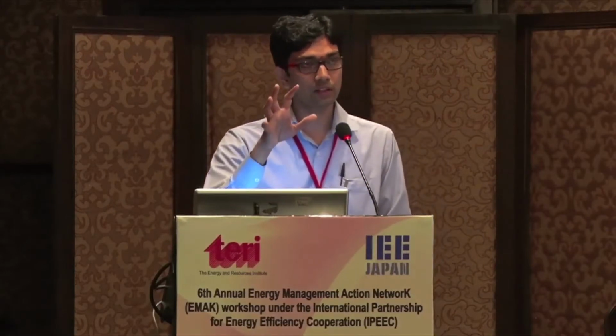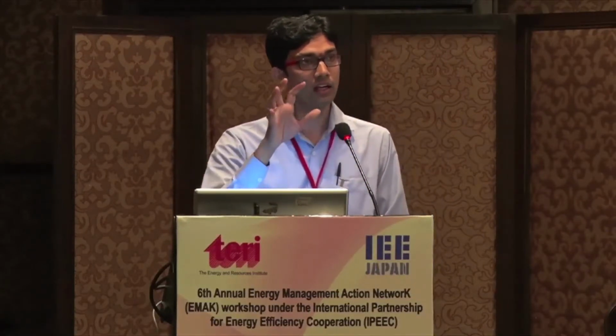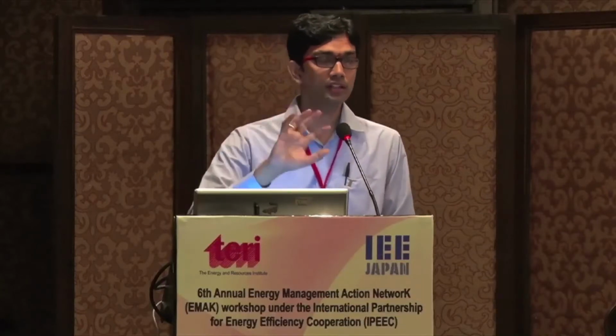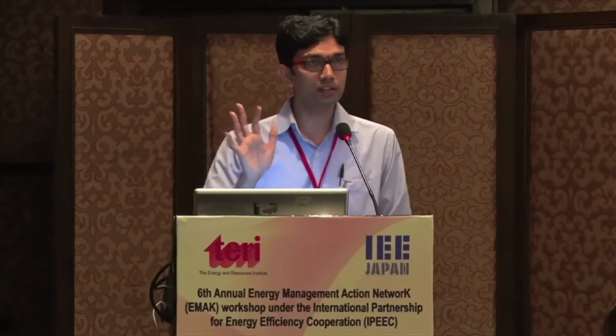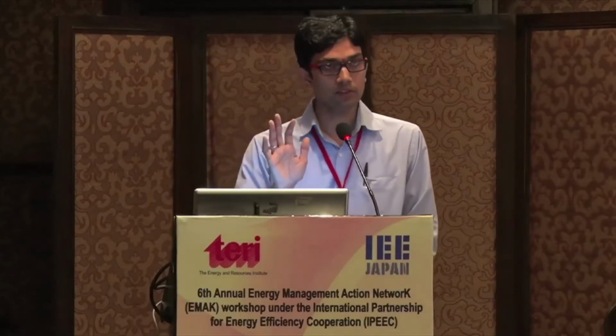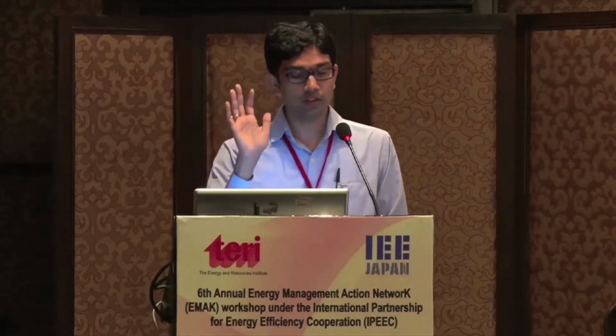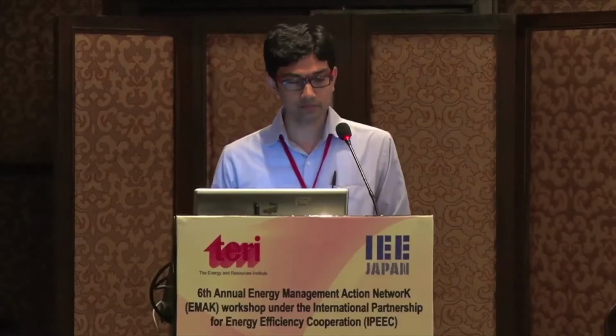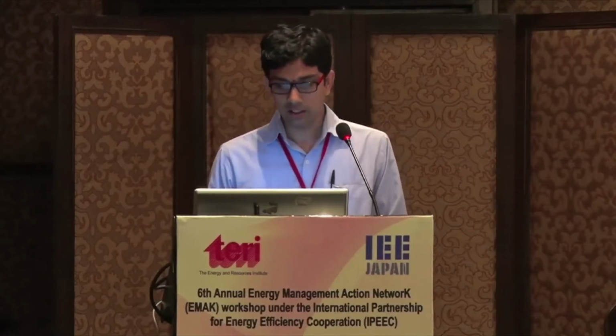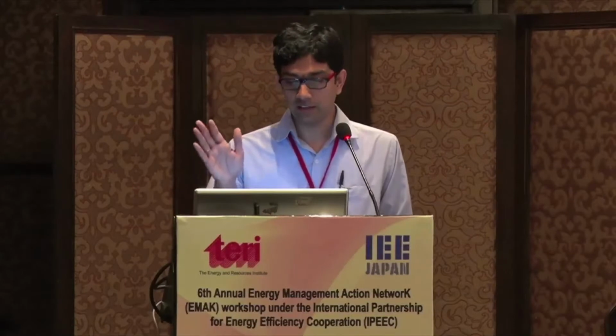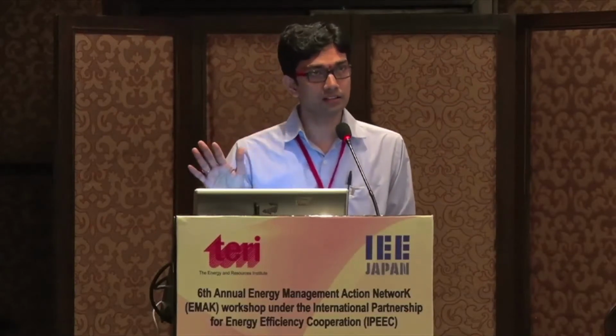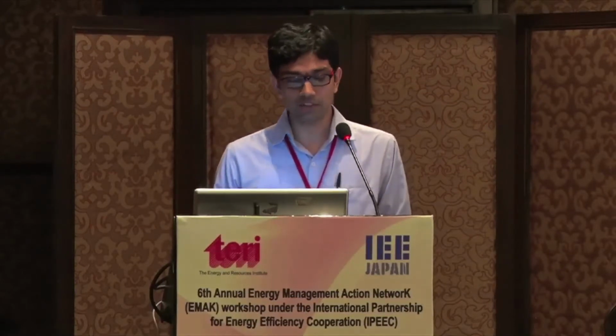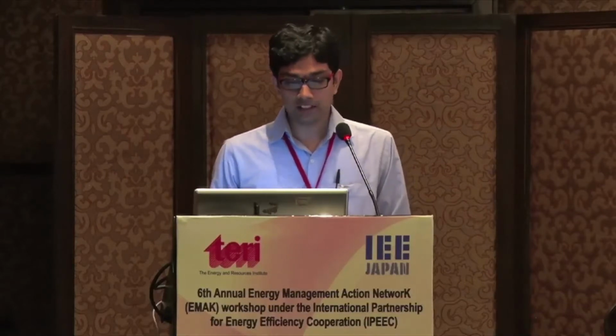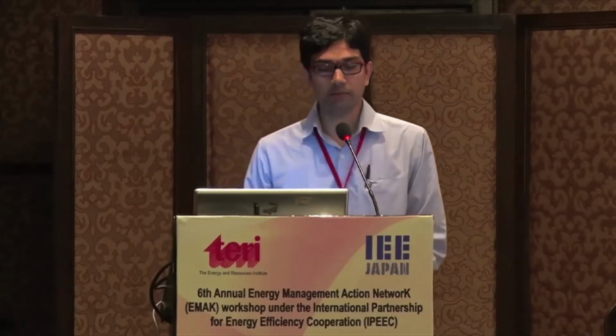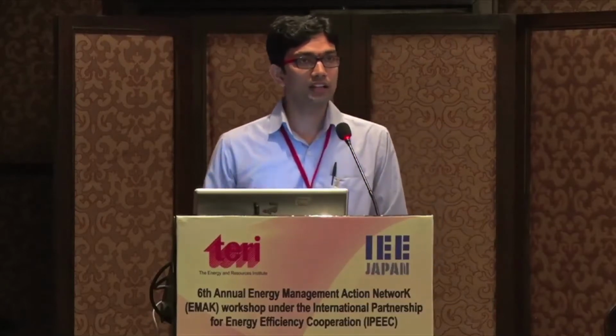Typically in any furnace, obviously there would be a material feeding door and a material exit door. So in almost all the units, we have found that the doors are wide open, and therefore there have been recommendations of reducing the opening and also improving the insulation. On the right side, you would see a picture where after our recommendation, they had installed an insulation door.